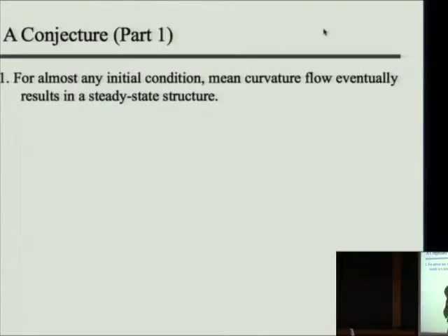Basically, you're just letting the areas change by proportion. I update the areas according to von Neumann's law. If I have to do any of the topological transitions I enumerated, I do them. And then I say, find the closest mechanically stable configuration, preserving the cell areas that you can.